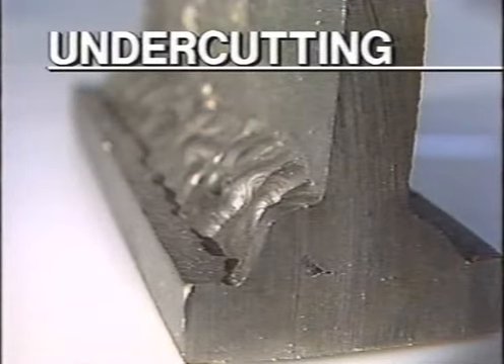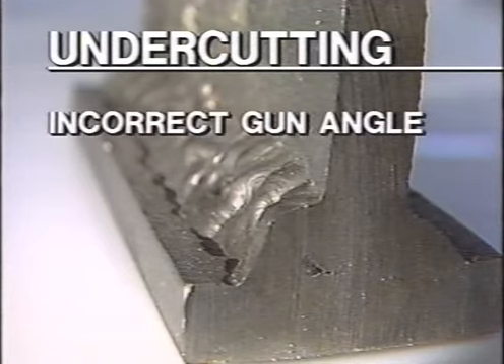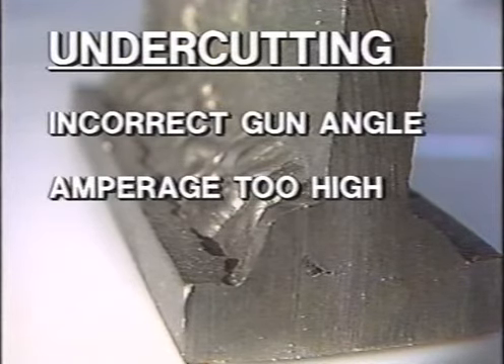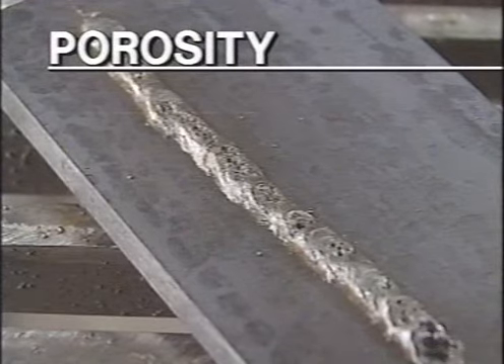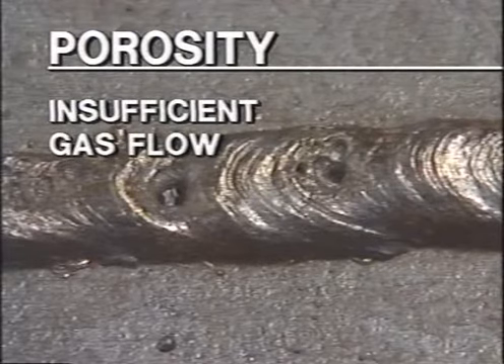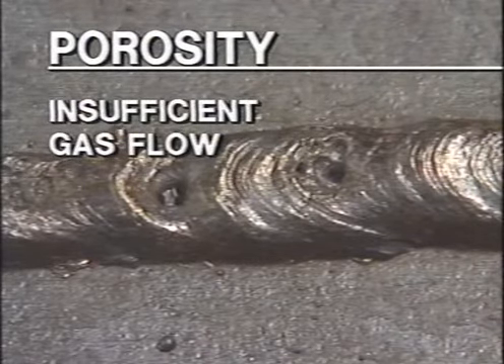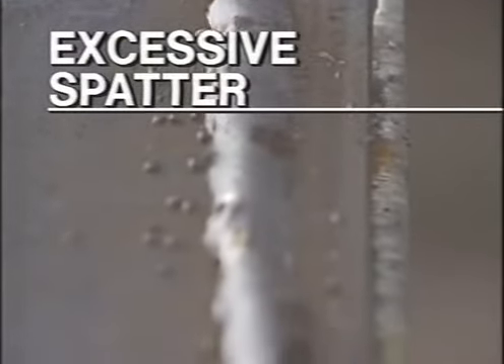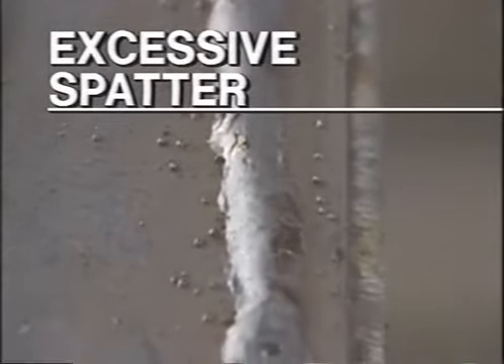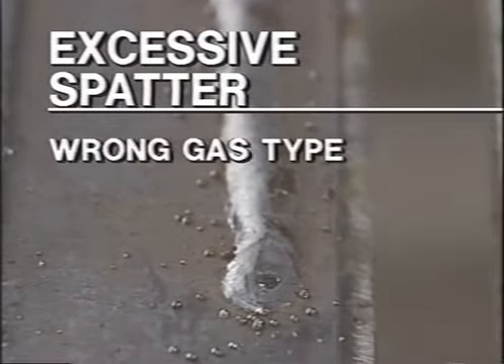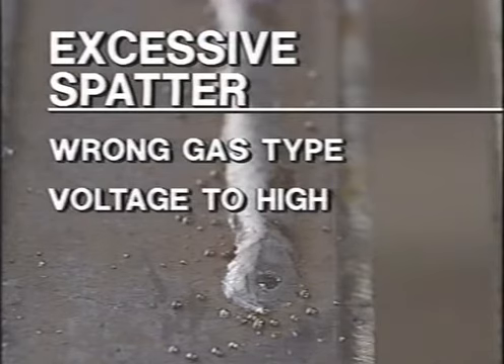Undercutting occurs as an irregular groove on the side of the weld. This can be caused by an incorrect gun angle or an amperage setting which is too high. Porosity occurs when tiny air bubbles are trapped in the weld. This is generally caused by insufficient gas flow. Excessive spatter around the weld area may occur for a number of different reasons, such as use of wrong gas type or the voltage selection being too high.